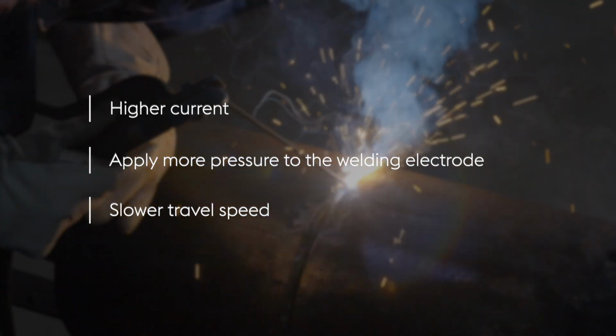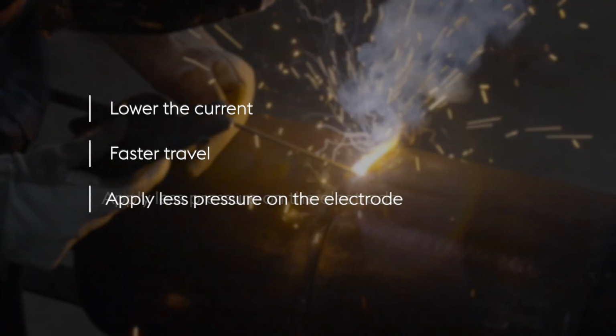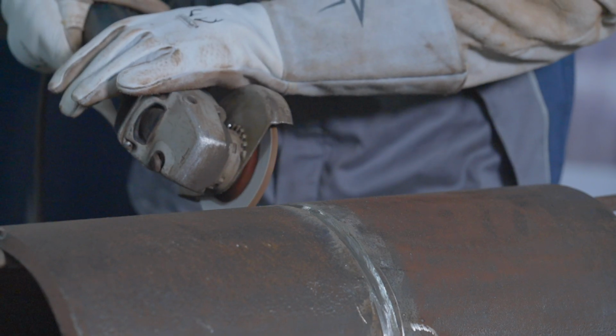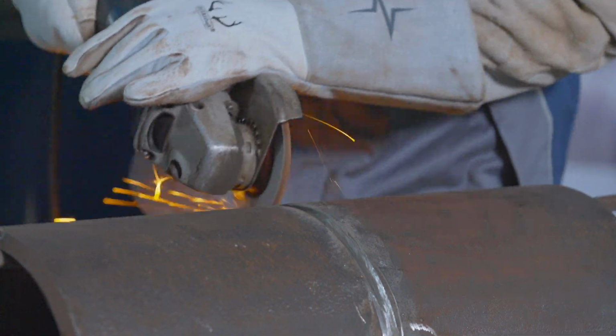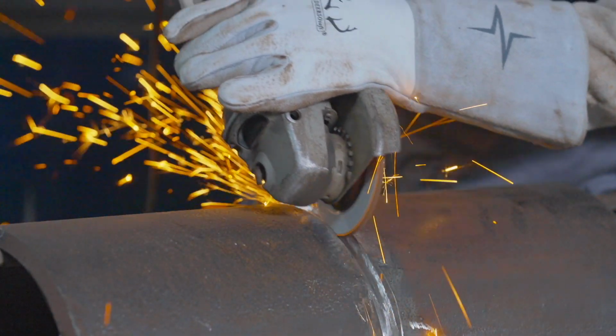If the keyhole is not seen by the welder, the electrode is not penetrating through to the inside of the pipe. The remedies for this would be higher current, apply more pressure to the welding electrode, and slow down your travel speed. If the keyhole becomes too large and difficult to control, the remedies would be lower the current, faster travel, and apply less pressure on the electrode. In order to prevent lateral slag inclusions seen in the weld radiograph, slight grinding of the stringer bead is essential.